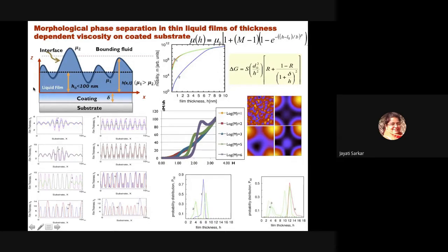You can see that in normal cases this gives rise to instabilities and droplets only. In this type of film, you can see that a secondary range of droplet thickness appears. These orange regions are where the primary droplets are, and this is a bimodal distribution of droplets, where the droplet in between has a different thickness than the droplets surrounding it, right?